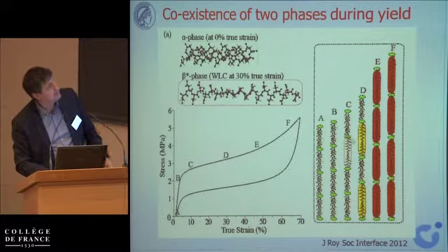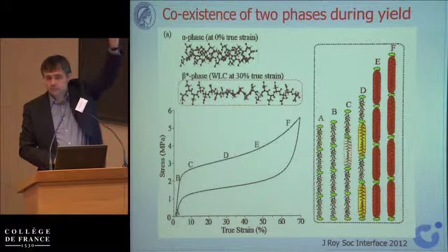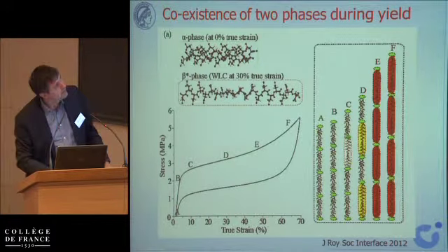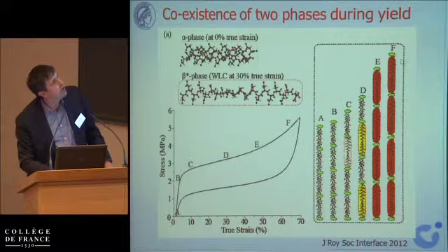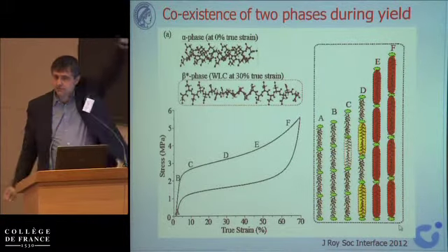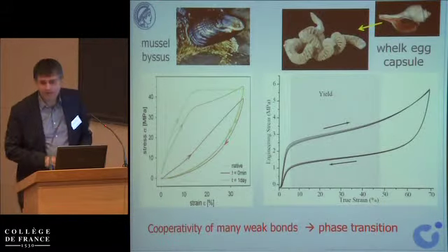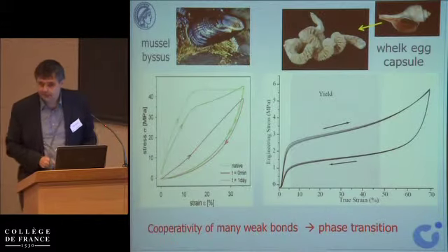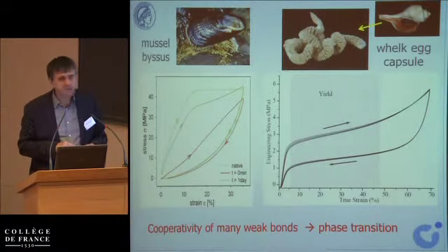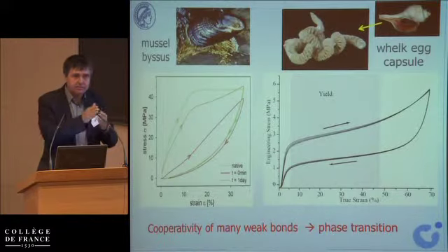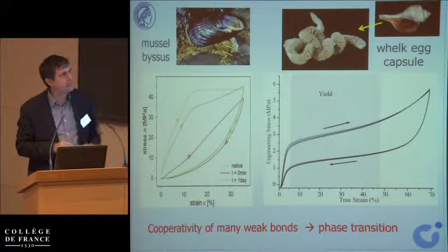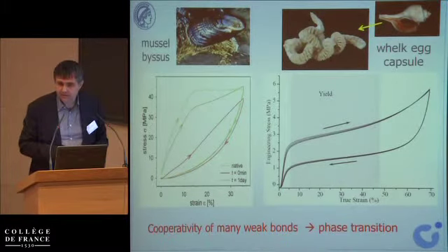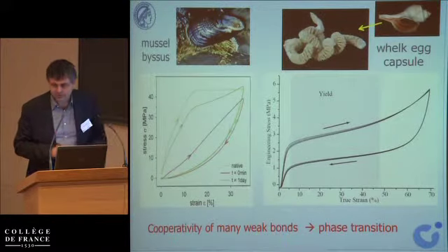the point B. And then something happens, a phase transformation occurs, and this phase transformation is actually a transformation from an alpha helix to an extended conformation of that molecule. And this is a sudden transformation. But of course, if the sudden transformation happens only in one of those four, there's a little bit of elongation. If you then transform another one, there is more, and then until you reach the point F, all the segments of that molecule have transformed into the extended conformation. So this is completely analogous, by the way, to what's going on in nickel-titanium fibers that you use to move your teeth around, where on stretching, you're changing one phase to another phase that has a bigger lattice spacing, and that allows what people call superelastic behavior. And actually, the nickel-titanium model works perfectly for these proteins.